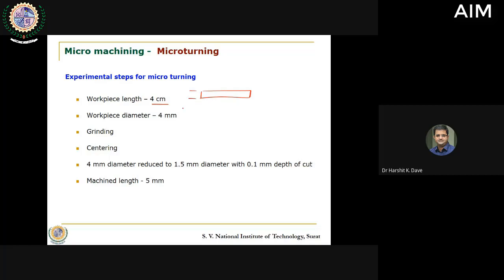What we tried to do was reduce this diameter from 4 mm to 1.5 mm, and later we went up to 0.5 mm also. In all these cases, we took a depth of cut of 0.1 mm, which is 100 microns, and the machining length that we took was up to 5 mm. So eventually this is what we tried to carry out.